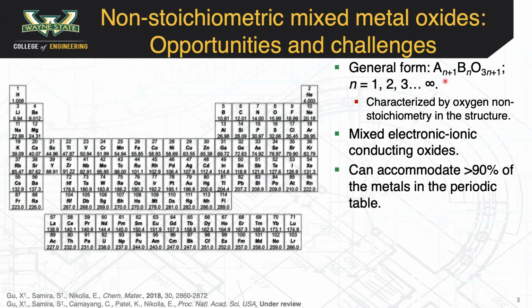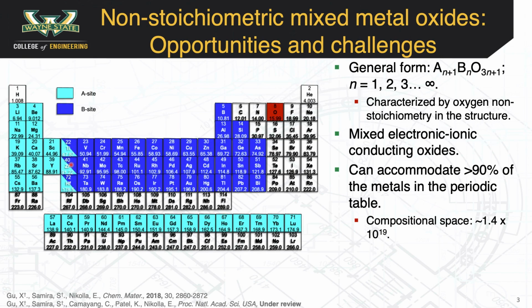Although I told you earlier that the A and the B sites are metals, I did not tell you what phase space they can encompass across the periodic table. If one were to use the periodic table as a toolbox to identify the A and the B site metals, it is observed that these oxides can encompass 90% of the metals in the periodic table, giving rise to a vast phase space of the order of 10 to the power 19 potential compositions. The A site is generally either the alkaline earth metals or the rare earth metals, while the B site is the catalytically active transition metal.